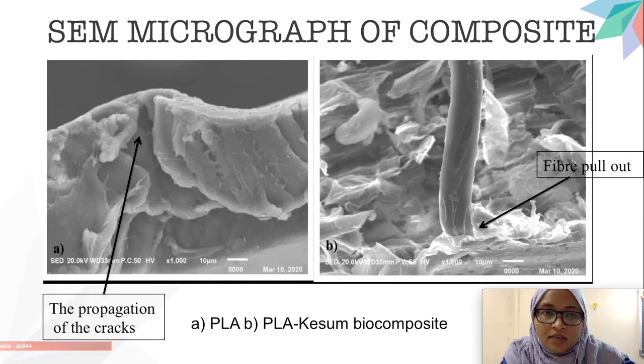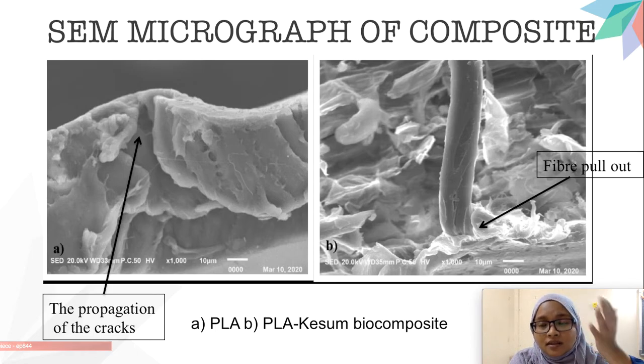Okay, next, the SEM micrograph of the composite. As you can see, in A, it is the crack propagation during the tensile test of PLA that leads to fracture as there is no grip that can delay the time for fracture to happen. Okay, for B, the PLA Kesum biocomposite, as you can see, the fiber pull out. The fiber pull out is due to the fracture of the fiber during the tensile test. Also, the fracture happens because of the presence of voids in the fiber itself.